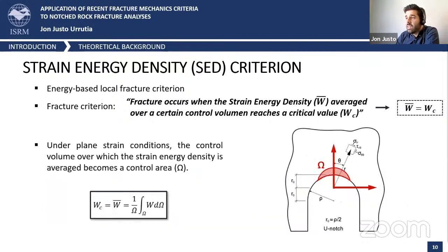This strain energy density is averaged over a control volume that in the case of plane strain conditions becomes a control area that's represented on the right of the slide. So what we have to do is to average the strain energy density in this area, and when this value reaches a critical value, fracture will occur according to this criterion.